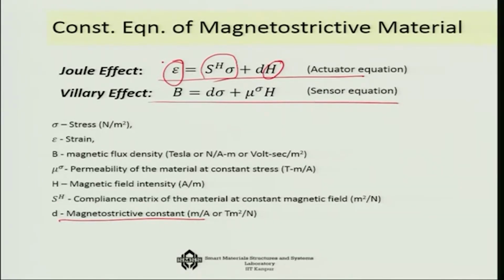Similarly, if you look at the Villari effect, which is more used for sensor development, here if there is a change of magnetic field intensity, then there will be a change in the magnetic flux density, which is fine. But in addition, if there is a change in stress, or a change in strain, then there will also be a change in the magnetic flux density B, and that can be captured as a change of voltage through a pickup coil. So that is the constitutive equation, which looks linear, but is actually linear only in a very small range, and this is used for developing actuators and sensors.